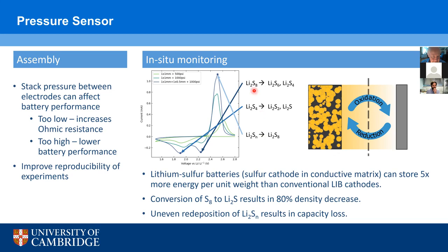During the conversion of elemental sulfur to lithium sulfide, there's a large decrease in density. So the lithium sulfide occupies 80% more space than the elemental sulfur, which leads to an increase in the volume. And this impacts the conductive host matrix because it applies a load which can lead to fracturing and loss of electrical connections. Another load that can affect the electrical connections is due to the redeposition of these polysulfides, which are soluble in the electrolyte and which shuttle between the 2 electrodes as they dissolve.